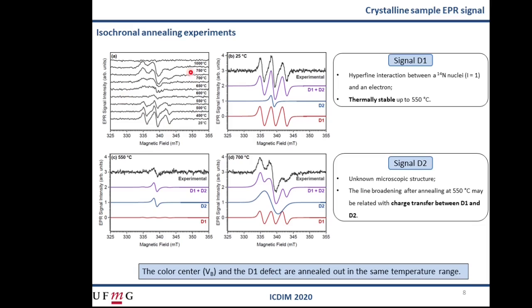To understand this annealing data, spectral simulations were done for all EPR spectra in this figure, considering a spin system composed of two parts, the D1 and D2 signals, and the simulations are shown in these three figures here. As can be seen from the sum of the signals, D1 plus D2, in all cases the simulated EPR spectra fit very well the experimental data. These EPR simulations make clear that above 550 degrees Celsius, the signal D2 exhibits a much broader line width and the hyperfine signal D1 disappears.